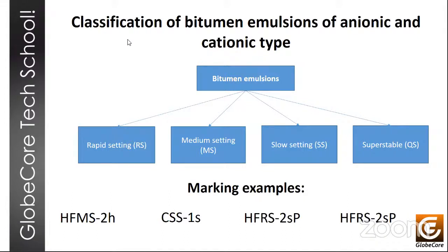For example, if we have an emulsion designated HFMS-2H, that is an anionic medium setting emulsion based on hard bitumen with low viscosity and the addition of special flotation agents. And if we have an emulsion designated CSS1S, that means it's a cationic slow setting emulsion with high viscosity, based on soft bitumen, basically a bitumen with a dilutant thinner.